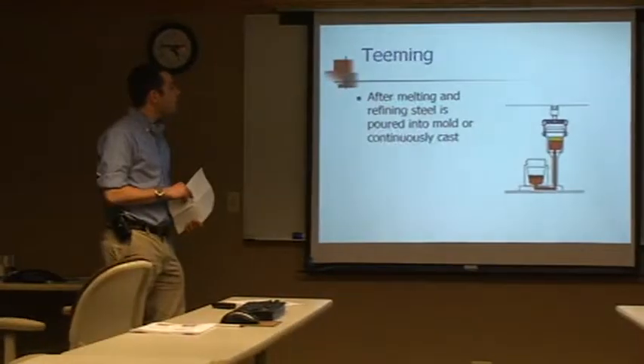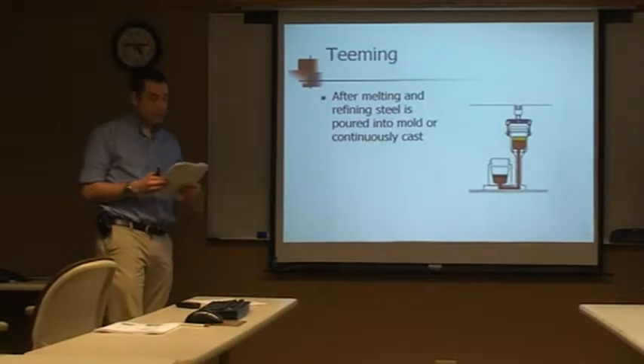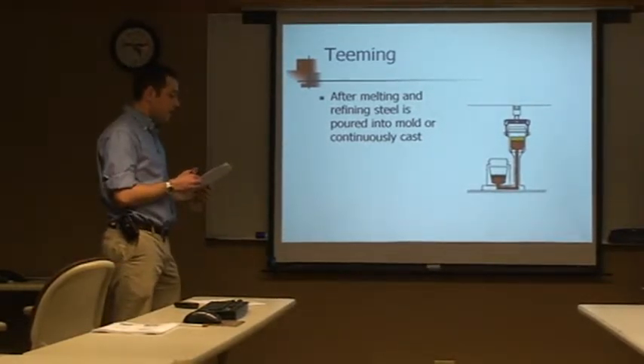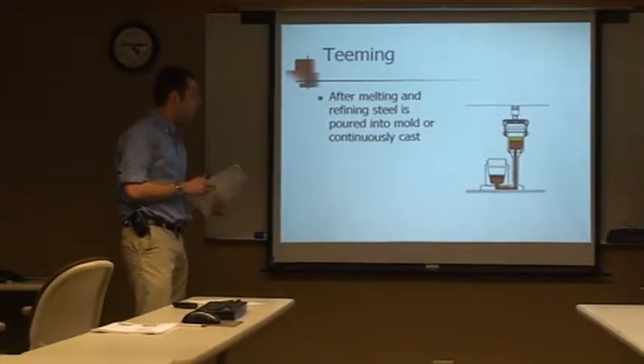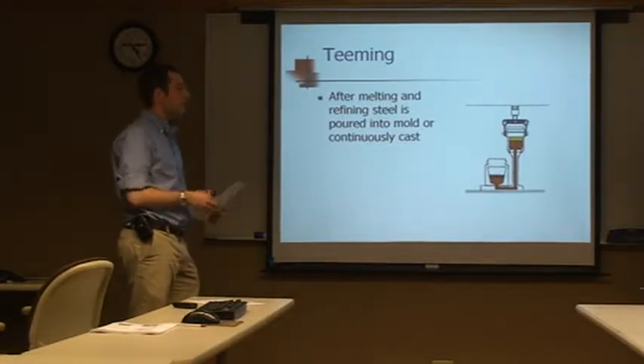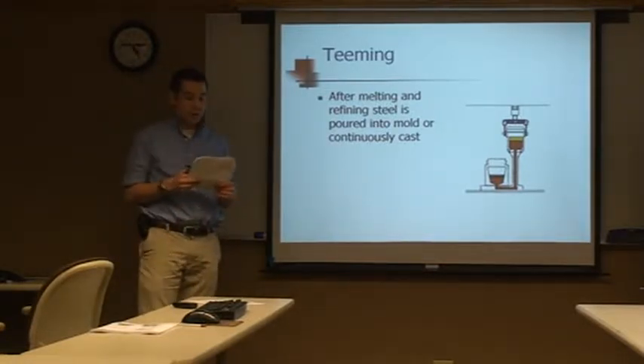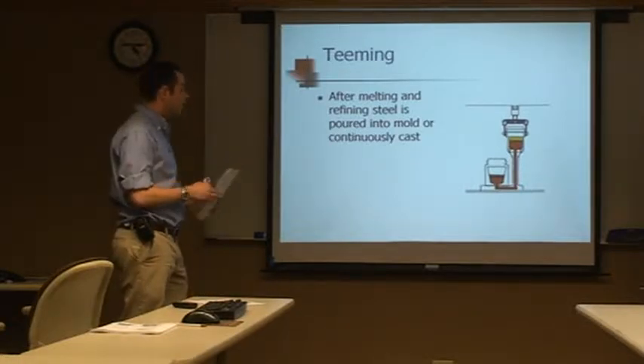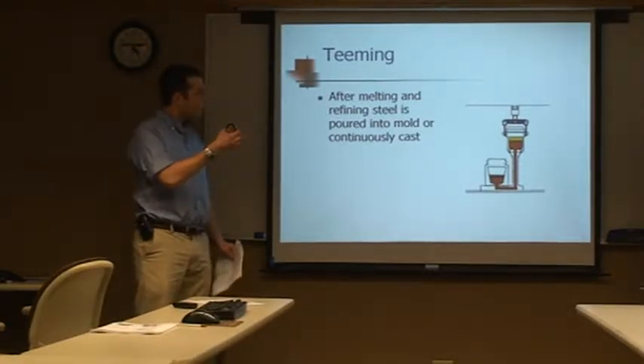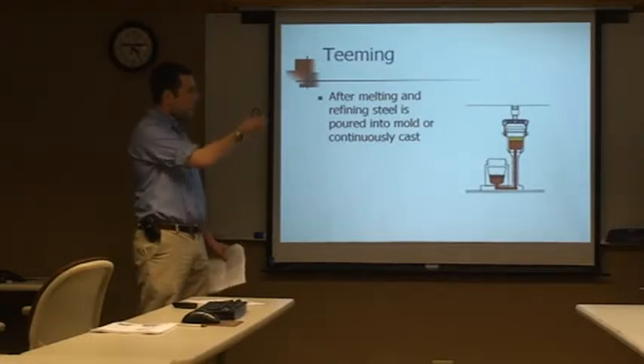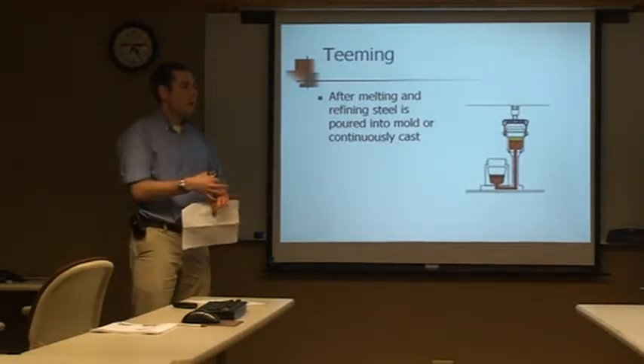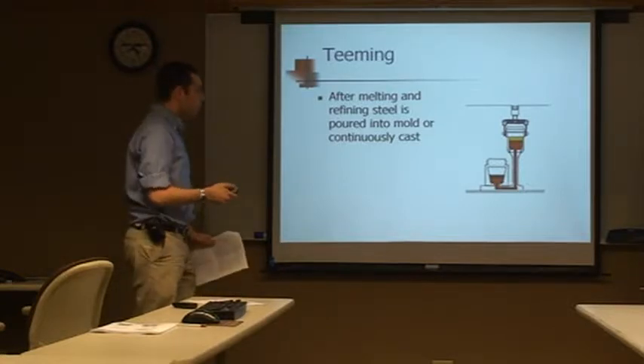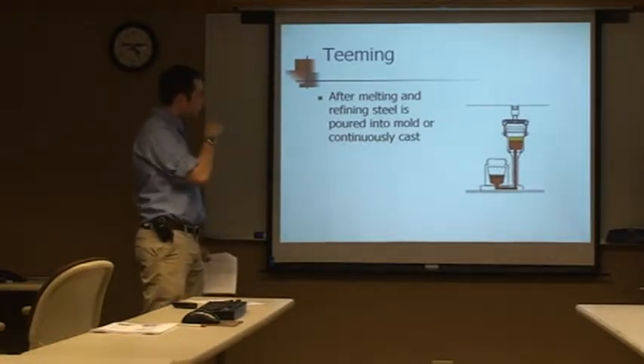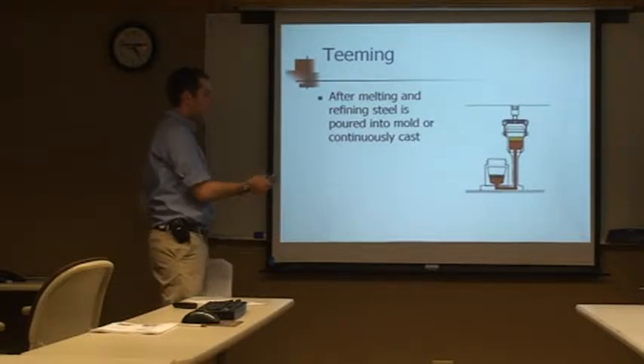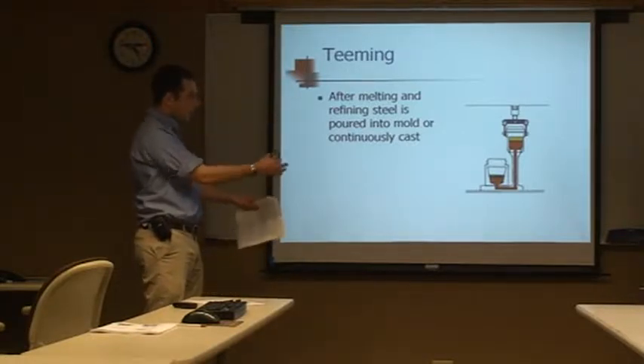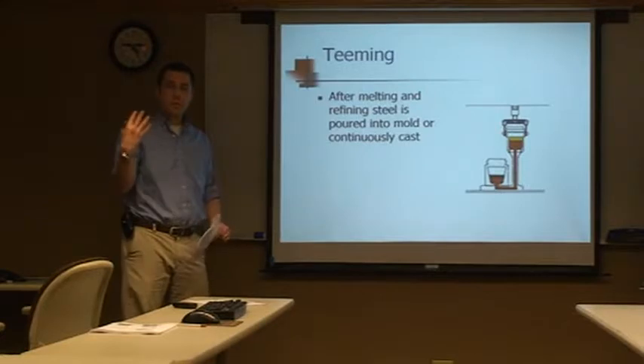So after all of the melting and refining is complete, the steel is sent for teeming into an ingot mold. And as Jim mentioned, at EQS we use a process called bottom pouring. That means instead of pouring the steel from the ladle directly into the top of the mold and filling it from the top, we open the ladle over a trumpet and have the steel flow down that trumpet into a series of runners and fill the molds from the bottom.